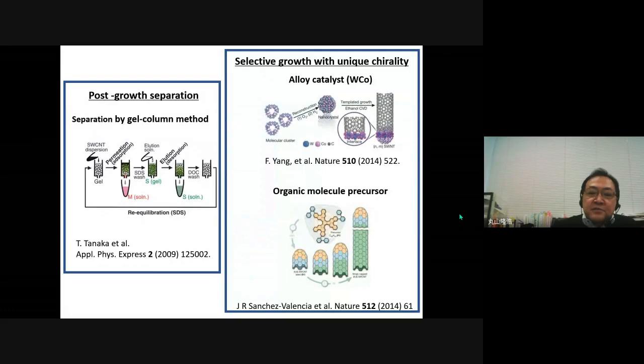So far, a few techniques have been reported to obtain SWCNTs with unique chirality. The methods are divided in two. One is the separation after nanotube growth. The AIST group in Japan obtained SWCNTs with unique chirality by the gel column separation technique. This technique enables separation of single-wall carbon nanotubes with various kinds of chirality. However, after the separation, contaminants were contained, which are unfavorable for applications. Therefore, selective growth of single-wall carbon nanotubes with unique chirality is desirable.